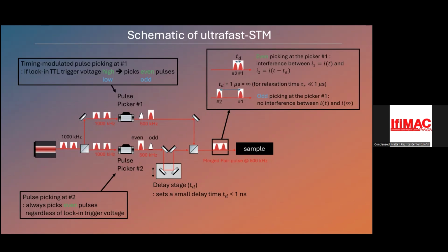Okay. And in our system, this is something really important. We are using a lock-in to measure the difference between two pulses: the current with two pulses being close, and the current with two pulses being pretty far apart. And the reason we do this is that by doing this, we get rid of the tip thermal expansion. Because remember, every time you hit the system with light, the tip is also getting hit with light. That means the tip is going to expand. So how do you separate actual data from tip data? The way we do it is by taking a difference between these two signals. Because for the purposes of the tip, whether the two pulses are separated by 100 femtoseconds or 1 picosecond makes no difference. So it's still going to expand thermally. So we just subtract the two signals from each other.